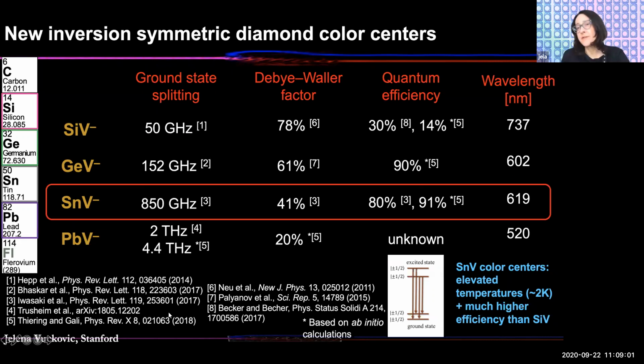color centers. All of them are inversion symmetric, and that means that they're, to the first order, immune to electric field, and they don't exhibit DC Stark shift. Again, to the first order, which means that they're more immune to the environment, and you can embed them inside of the structure and so on. But the reason why we're more interested in tin vacancies than silicon vacancies is because they have much larger ground state splitting, from 50 gigahertz to 850 gigahertz, which means that they don't suffer from phonon decoherence processes that require silicon vacancies to operate at millikelvin temperatures for the best results.